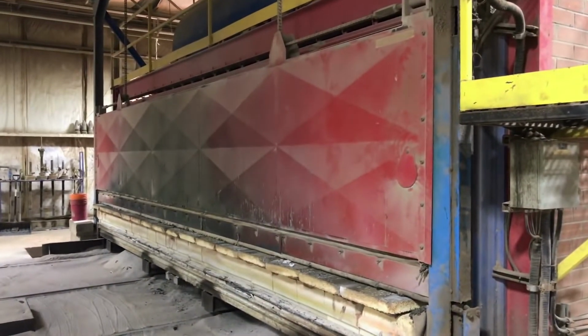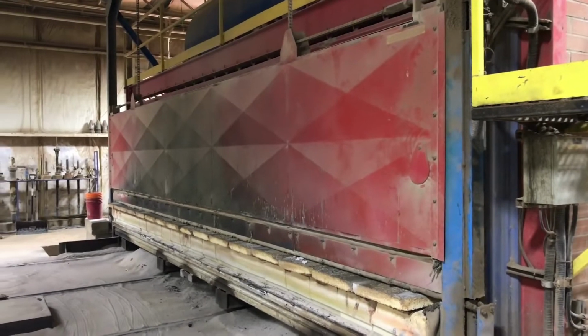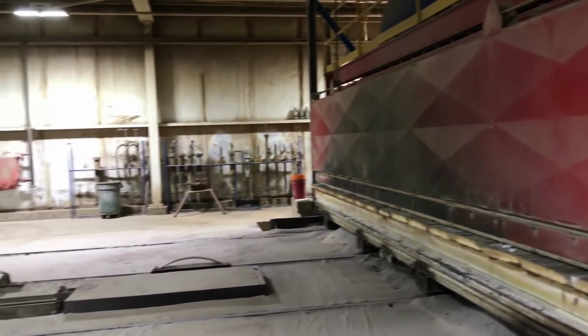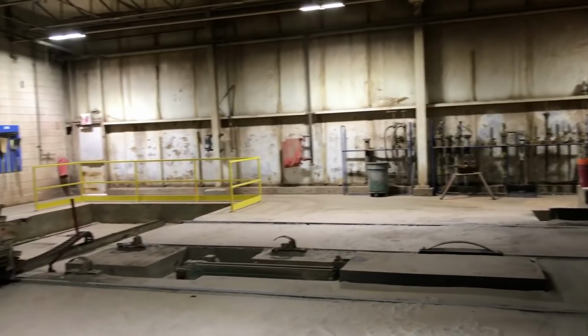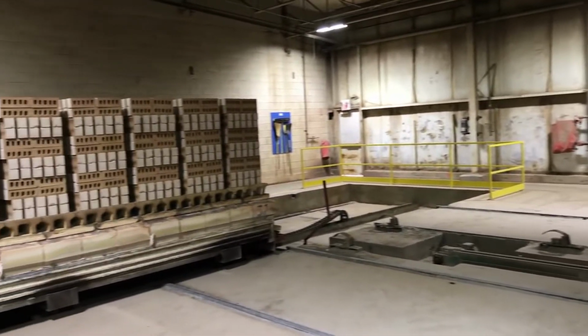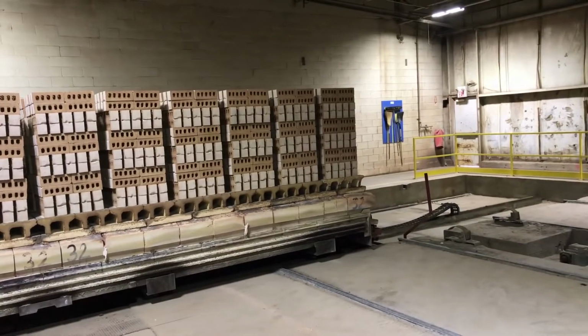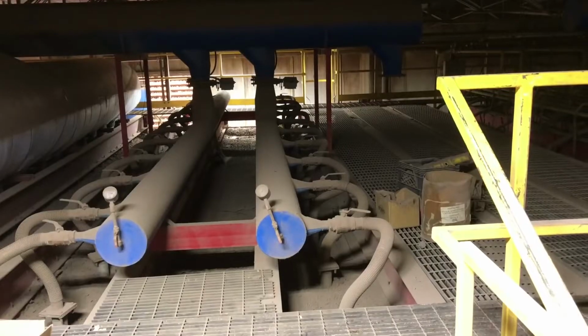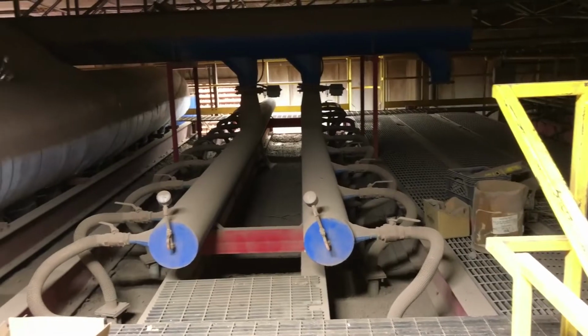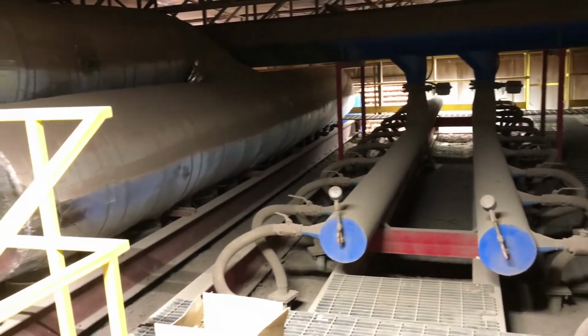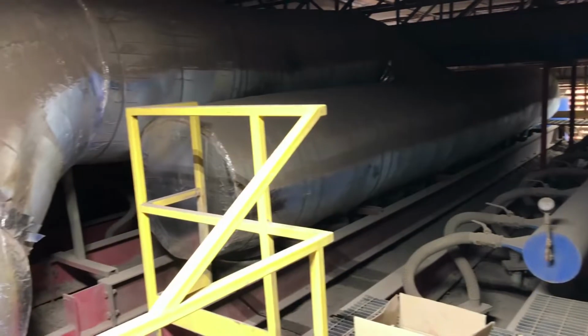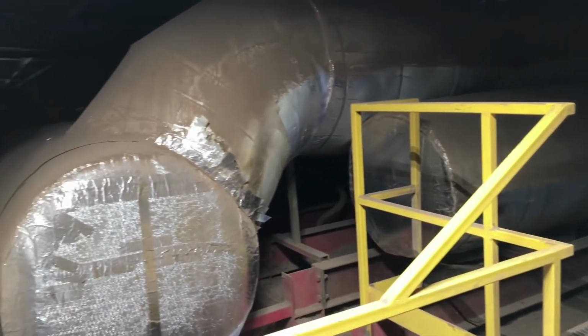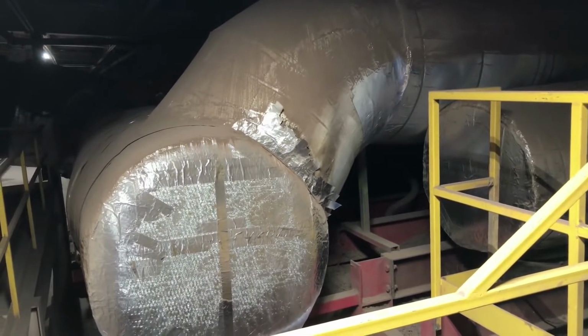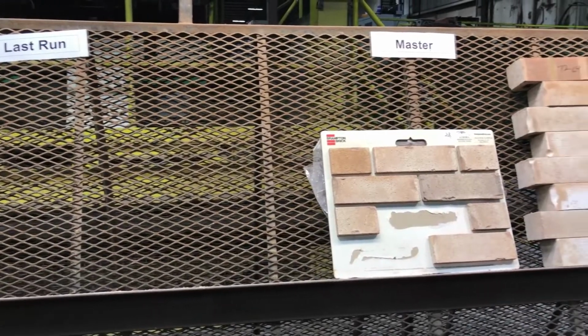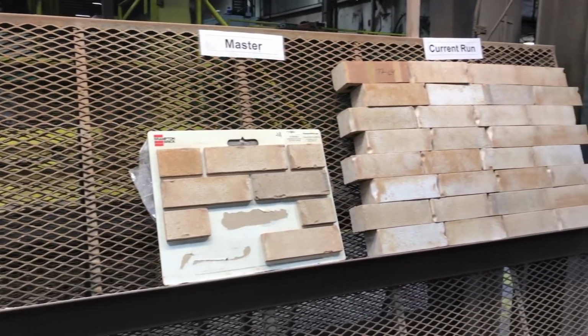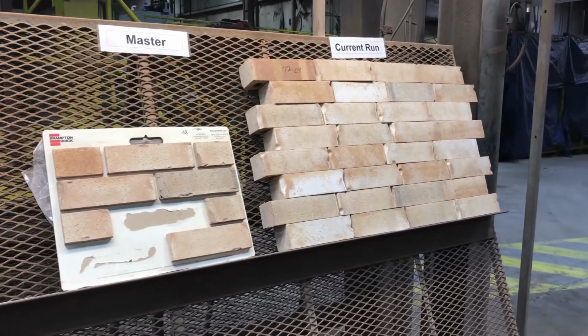Now the interesting thing is, even though it was very hot in the kiln, at least in the middle part, the bricks are just slightly warm to the touch as they come out. And the reason for that is because all of the heat in the kiln, after it's done its job, has been reclaimed for another purpose. That other purpose is to dry the bricks completely before they go into the kiln. The hot air extracted from the kiln travels through these insulated ducts. Even though there are many checks during the manufacturing process, the finished product is visually checked against a set of master bricks.